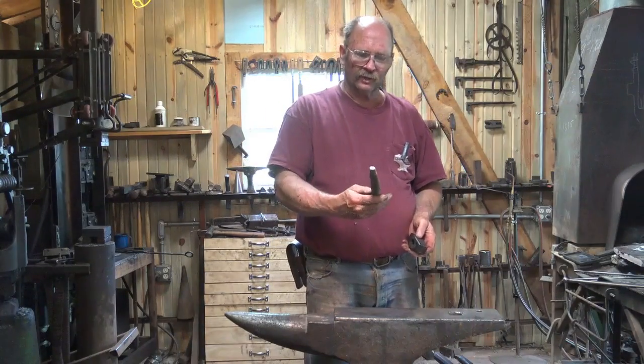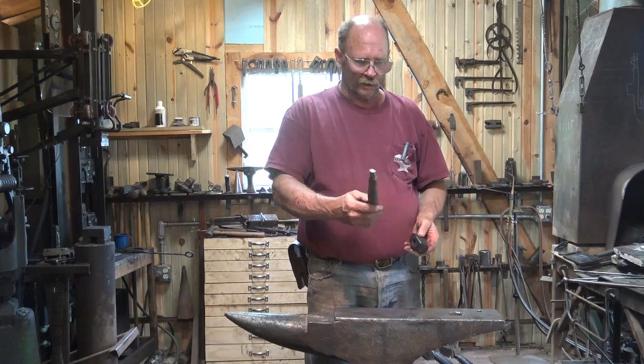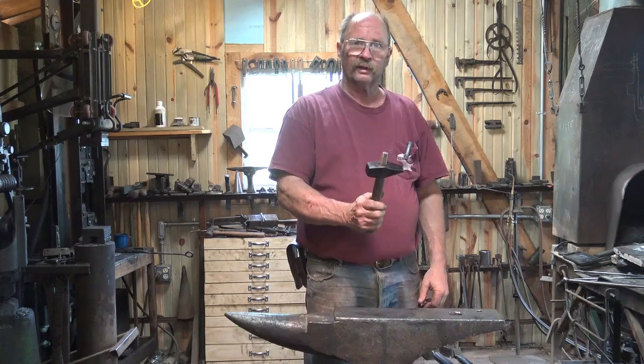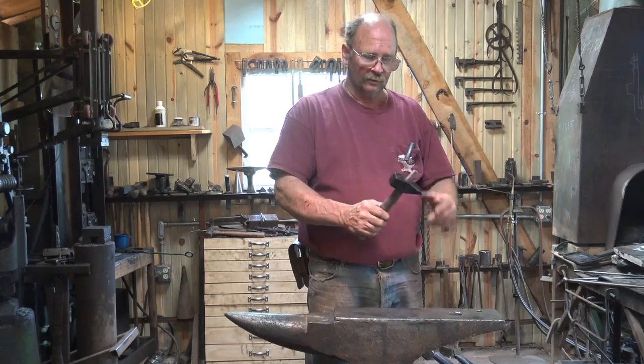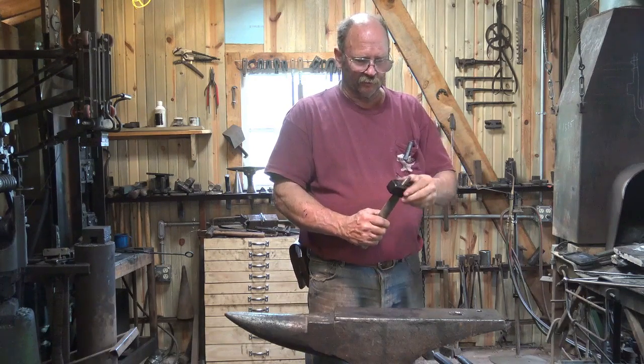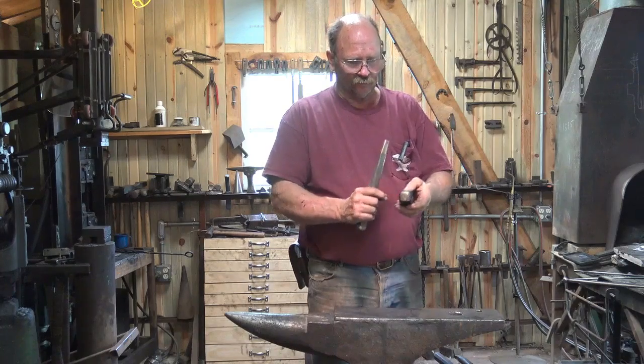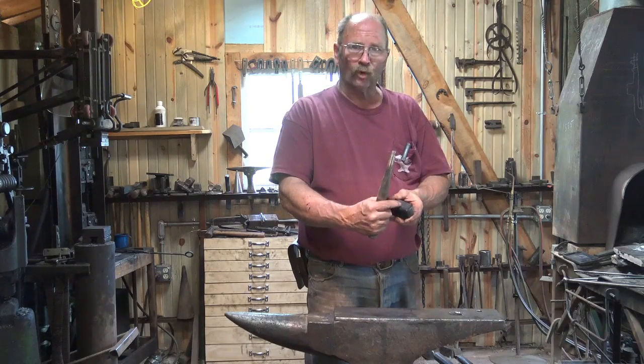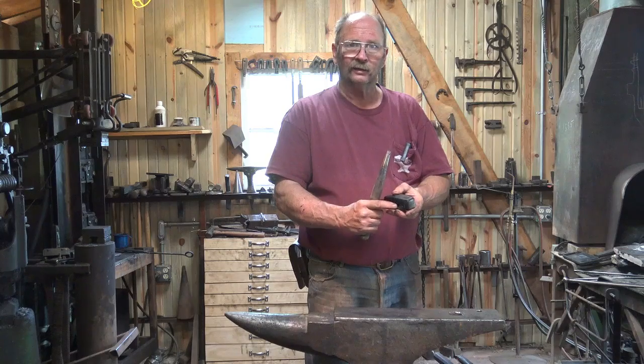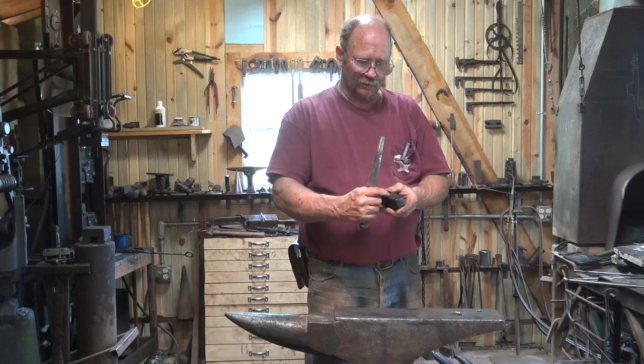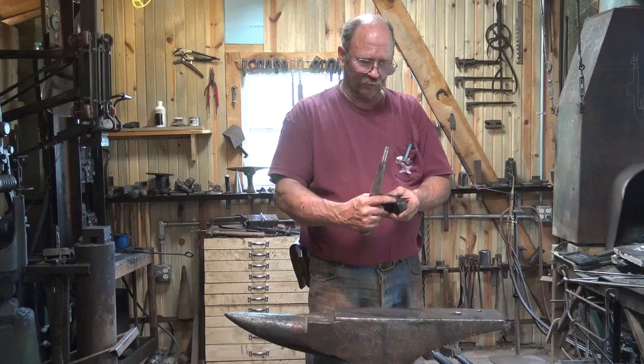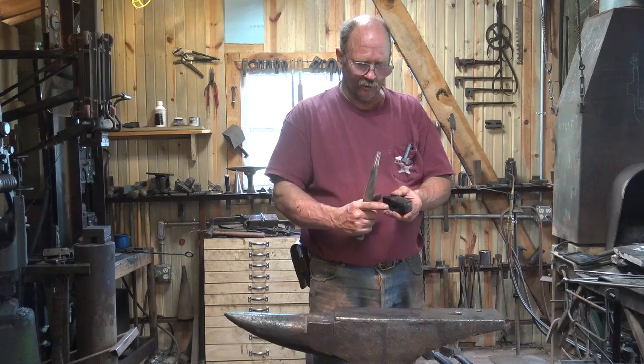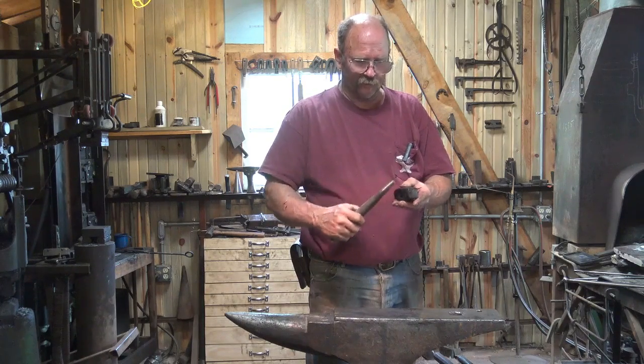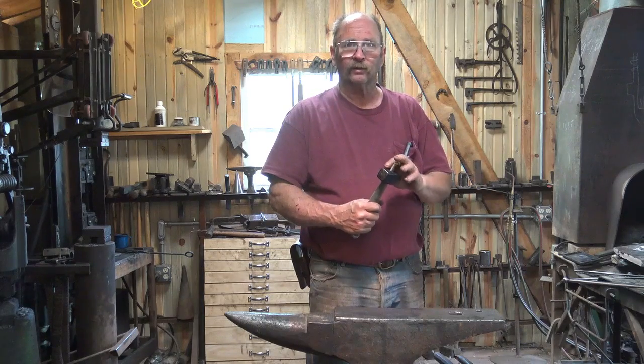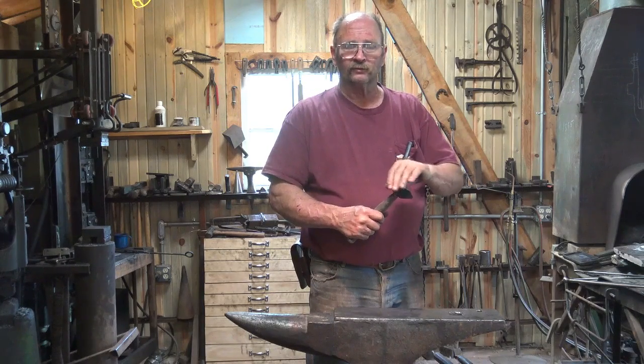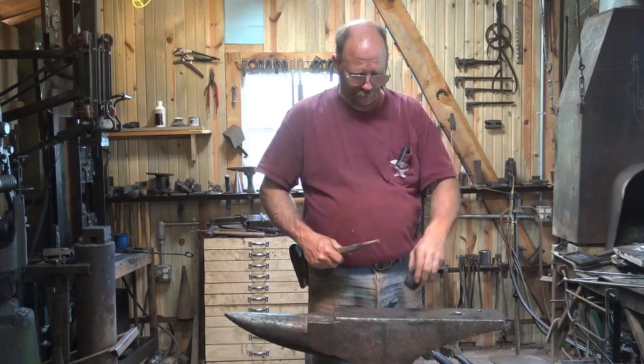And the secondary method of tempering, and the method we'll use for our second tempering, is to heat up something that is shaped roughly like your drift to red hot and drop the hammerhead over the red hot pin, and then rotate it every now and then. You'll have to use a pair of tongs. And this will heat this area up more than the head and the peen, and allow a variable temper. So this stays fairly hard on both ends, but is softer in the middle, because the eye is where it might crack, other than chipping at the face because you did something like hitting your anvil with it.